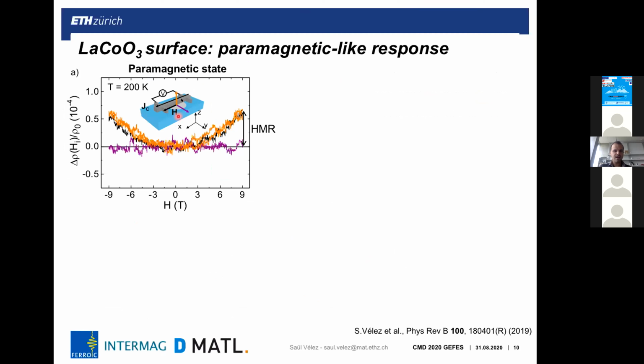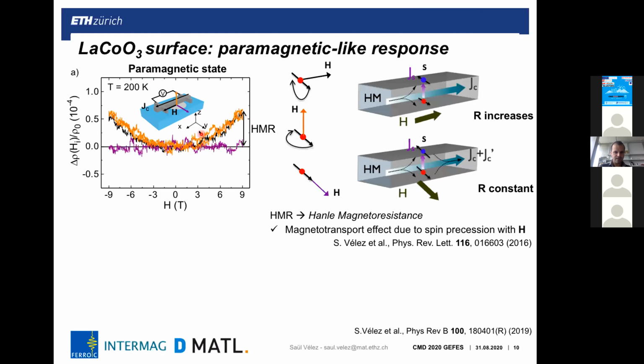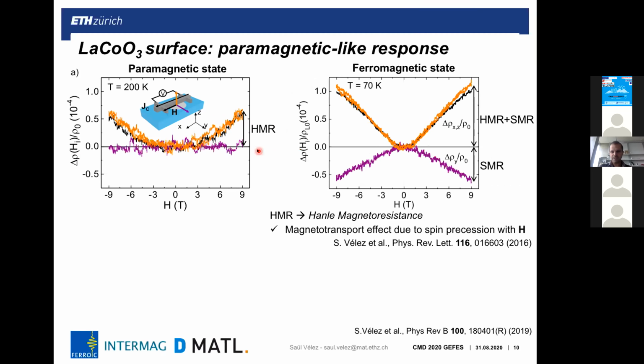So the idea is that we measure at high temperatures, above the transition temperature of the system. We measure the resistance, and we see that this exhibits the Hanle magnetoresistance. Basically, what we observe is an increase of the resistance when the magnetic field is applied perpendicular to the spins. This is related to the spin precession of the spins generated in the magnetic layer, and this is an effect intrinsic to the heavy metal. When we apply the field parallel to the spins, there is no change because you cannot make the spins precess. Now if we measure at lower temperature, below the Curie temperature, we observe an additional magnetoresistance along the y direction, and this is directly the spin Hall magnetoresistance, because the Hanle magnetoresistance cannot lead to this magnetotransport.